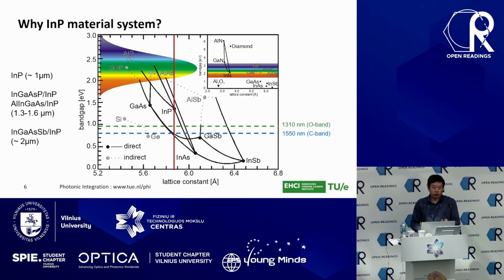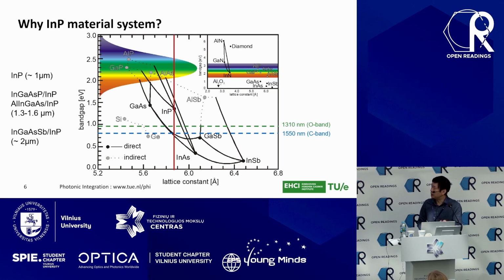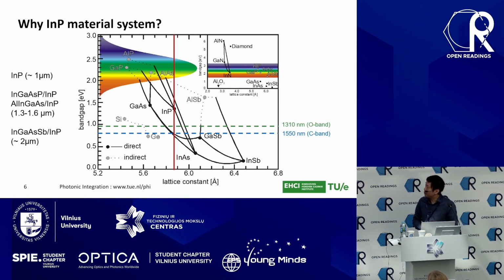So the bandgap tunability starts from the intrinsic bandgap of indium phosphide, which corresponds to about 1 micrometer of wavelength, and then slightly longer is the quaternary material containing indium gallium arsenide phosphide or aluminum containing compounds, which covers the typical near infrared. And we can also achieve a slightly longer wavelength up to 2 or 2.1 micrometer by adding antimony into it.